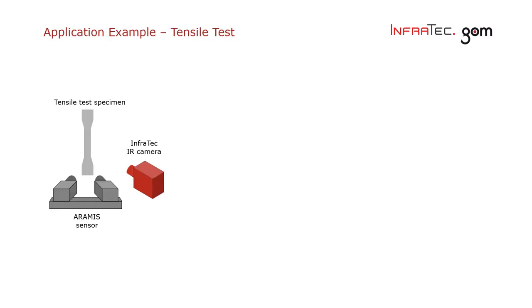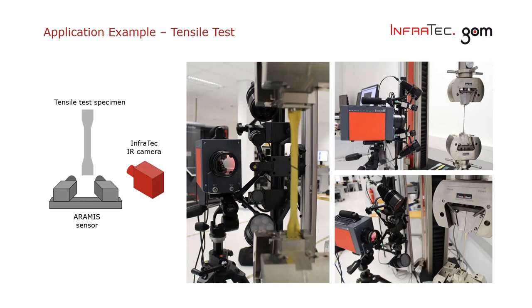An application example, as we have seen before on some slides, tensile test here. So the Aramis sensor is positioned in front of the test part as well as the IR camera. In reality, this looks like you see on these images over here. The Aramis sensor here, on an adjustable base, is aligned horizontally to the test specimen. You may ask yourself why we do it like that, but the issue is that these cameras do have a 4:3 ratio, from the size of the camera chip and the resolution, so we want to maximize the resolution on the test specimen. The InfraTec IR camera is positioned next to the specimen here, so it both looks on the same field of view on the same specimen so that we then later can correlate both measurement results together.